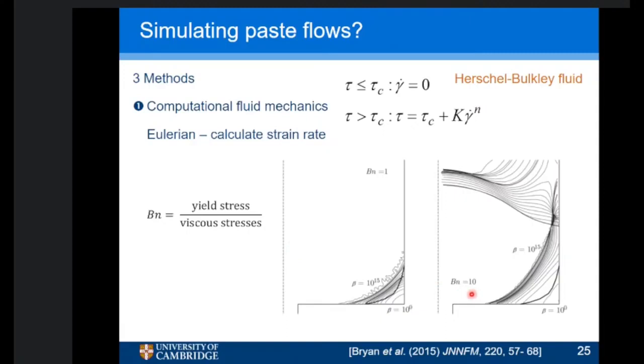If you go to a Bingham number of 10, which means it's 10 times more stiff in terms of yield stress, you can see it makes a big difference in terms of the size of this, let's call it a static zone in the corner. But also we see that the region where it starts to shear starts to come down and get quite close to the die entry. So up here, everything is shearing. Here, these are effectively a static region in the barrel. And this is information you need if you're designing a die, because you need to make sure that the barrel is the right shape so you don't get these static zones in the wrong places.